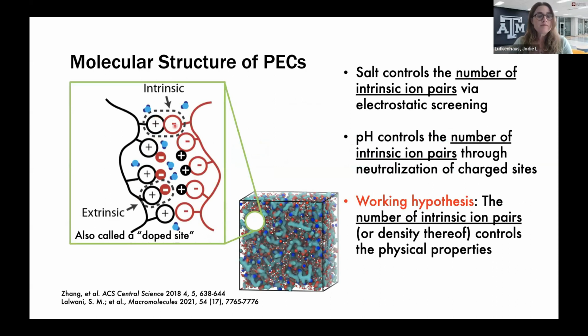So when these polymer repeat units of opposite charge come together and associate, we call that an intrinsic ion pair, kind of like an internal ion pair. And then the opposite of that is a charge group on the polyelectrolyte that's associated with a small counter ion, so maybe like a sodium or a chloride. So your complex is going to consist of a mixture of these intrinsic ion pairs that act as crosslinks, and then these extrinsic ion pairs. And in the literature, people also call these extrinsic ion pairs doped sites because they're doped or compensated by a small counter ion.